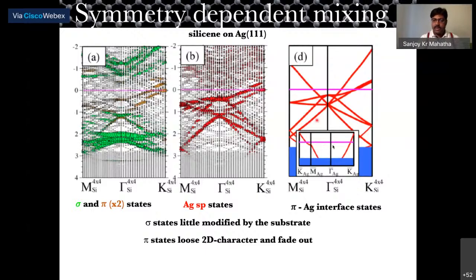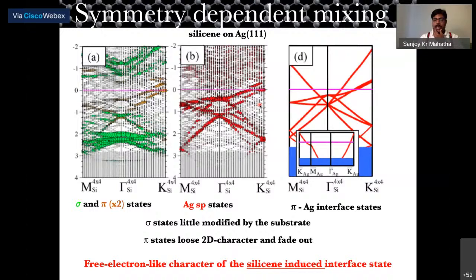The silver has a very simple band structure, like this, a parabolic band like this. And if you fold them into a 4 by 4 Brillouin zone, this is what you will get. Okay, this one. And if you compare, this band is basically this one. Okay, and this flat band is basically this one. So it is basically nothing but coming from silver 111. This is basically a silicene-induced interface state. So you get this when you put silicene on top of silver 111, but the orbital contribution of this band says that it is coming only from silver 111, or most of it is coming from silver 111.